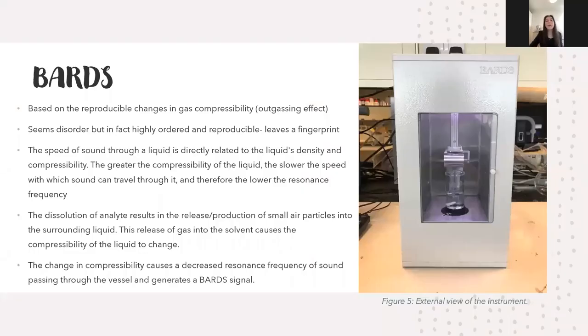BARDS is a complementary approach to surrogate testing. It's standard dissolution testing based, and the speed of real-time data acquisition and how the data can be extrapolated matches that of standard regulatory methods. A compound generates a unique acoustic profile at a fixed solvent volume and analyte concentration. The dissolution of an analyte introduces gases trapped between and within particles and reduces gas solubility in solution. This leads to the reproducible change of the compressibility of solution due to the outgassing effect, which acts to slow down the speed of sound.